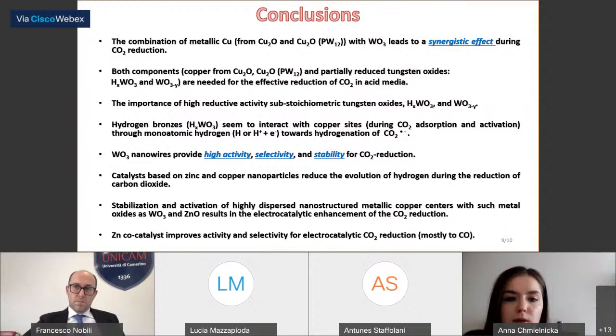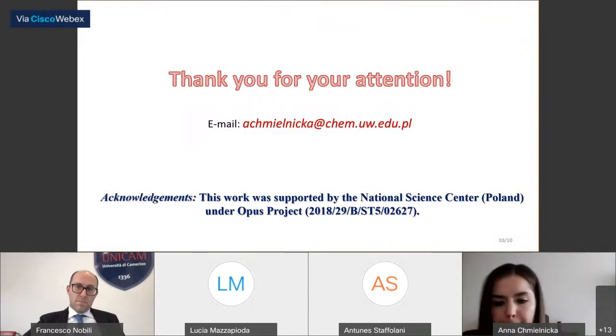Stabilization and activation of highly dispersed nanostructured metallic copper centers with such metal oxides as tungsten oxide and zinc oxide results in electrocatalytic enhancement of CO2 reduction, and the zinc co-catalyst improves activity and selectivity for electrocatalytic CO2 reduction, mostly to carbon monoxide. And thank you for your attention.